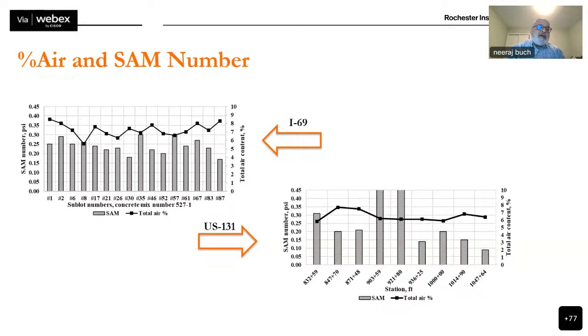And then we also ran another test using the super air meter. And I'm not sure if the super air meter has made its way to India. But the super air meter is a modification of the conventional air test that we are all familiar with. But what the super air meter does is it allows the contractor or the testing company to measure not only the percent or the volume of entrained air, but it also gives you a sense of the distribution of the air bubbles in the concrete, which is also a critical piece in determining the freeze thaw susceptibility or the freeze thaw durability of the concrete.